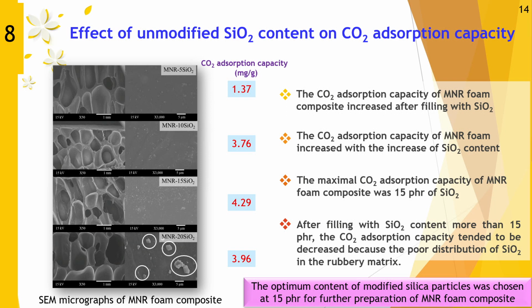And here I would like to show you the effect of unmodified silica particles on the carbon dioxide adsorption capacity. The carbon dioxide adsorption capacity of the modified natural rubber foam increases after filling with the silica content. And the carbon dioxide adsorption capacity of the modified natural rubber increases with increasing the silica content. And it reaches the maximum by using the silica content up to 15 phr.